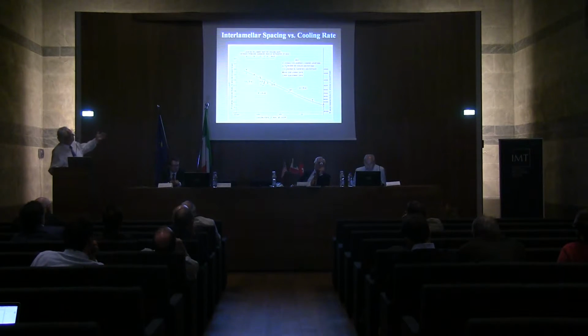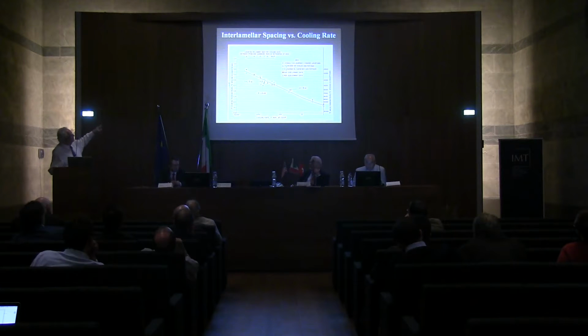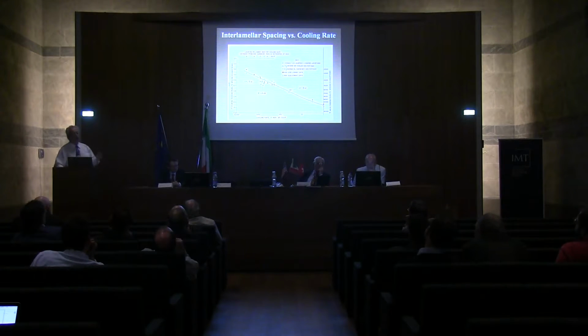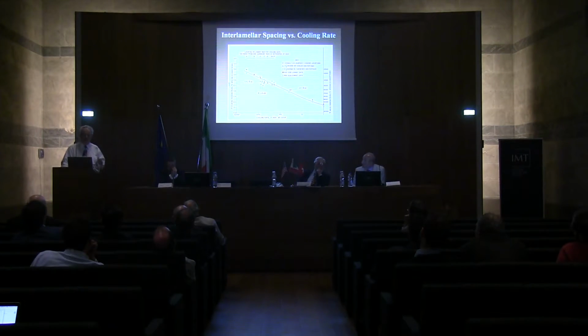So when we look at the cooling rate, on the y-axis on the left is the log of the mean random interlamellar spacing. If you measure a directed spacing, you can't do much with that. What you want to do is a random orientation, use like a circular test grid, and get a mean random spacing, because that's exactly twice the mean true spacing. And that's been proven theoretically in the literature.